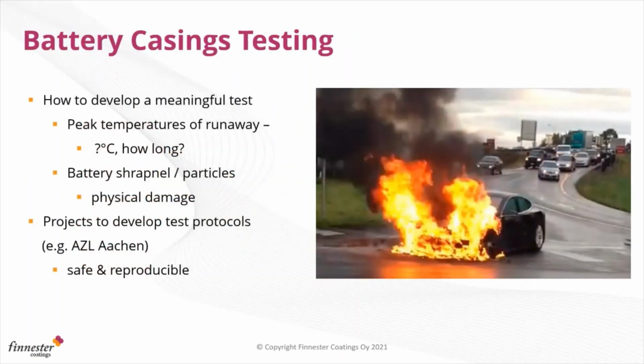For example, in battery casings, but also applying to hydrogen cylinders, there's a big question about how we can develop a real, meaningful test. It's not just about the temperatures and times needed, but also what happens when you have this thermal runaway, where the battery disintegrates and basically explodes into particles, also damaging the inside surface of the casing. We've got a combination of physical damage and very high temperatures, well over 1,000 centigrade. There are some projects underway, including the project at AZL in Aachen, to develop these test protocols and come to some general agreement within the industry on what needs to be done. How do we prove that the casing is fit for use?